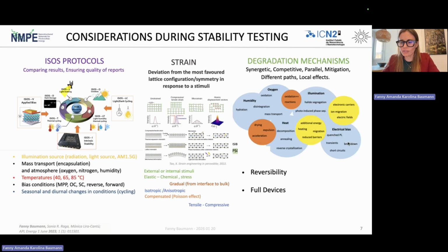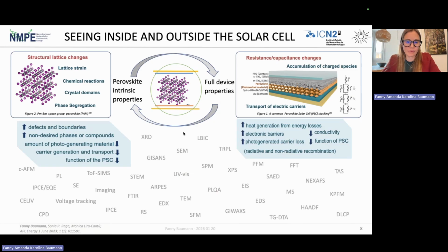It's also important to consider reversibility of certain degradation mechanisms and the importance of testing full perovskite solar cell devices and not only a single layer or a half stack. With that said, we have a challenge presented to us, and that is to relate the perovskite intrinsic properties to what we can see in the full device. And there are several types of methods which we can use for in-operando characterization, but we have chosen photoluminescence, X-ray diffraction, and impedance spectroscopy.